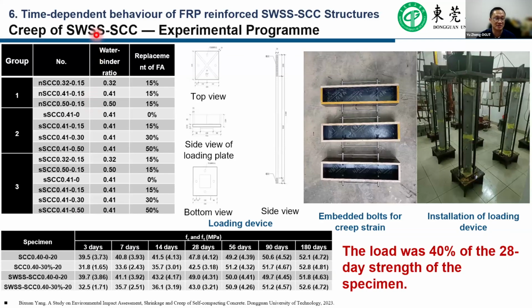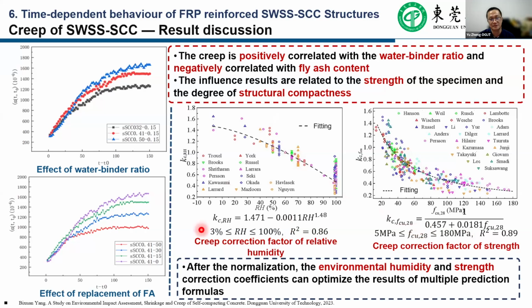In the second part, for this concrete material, we studied the creep behavior. It can be found that the current design codes cannot be used directly for this seawater and sea sand self-compacting concrete. The prediction formula needs to be modified with some coefficients, in view of the correlation with the increase of concrete strength, and the environmental relative humidity has a strong influence on the test results. Among them, the modified parameters were obtained by fitting the results from the normalization of relevant literature, and the modified result was obtained using the Bazant model. After the normalization, the environmental humidity and strength correction coefficients can be optimized, and the results of the multiple prediction formulas can be optimized.